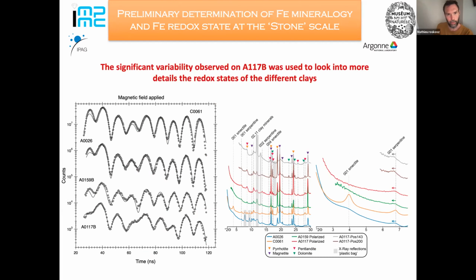So this is the same picture, the same spectra as shown previously. These are the polarized spectra, but as you can see, we were very lucky on A117b, because this one is pretty different from the others. Looking at the X-ray diffraction collected on site, you can see also one large difference. The big difference with 117 as compared to the other ones is the lack of the 001 reflection of smectites that you find at low angle.